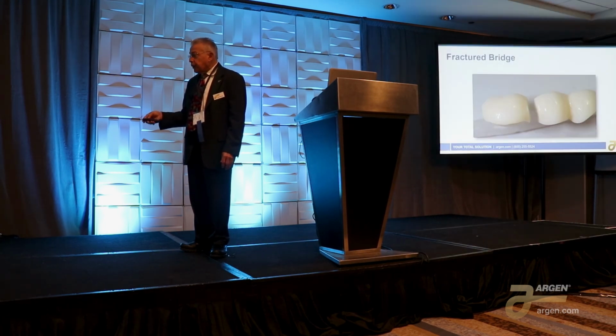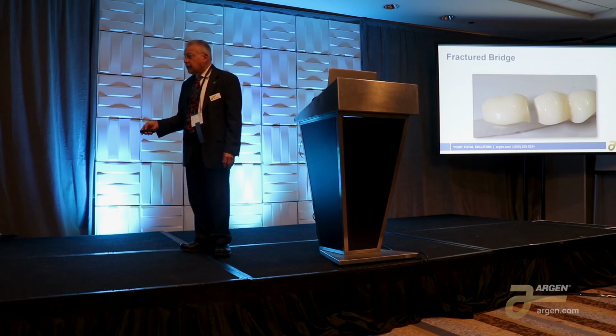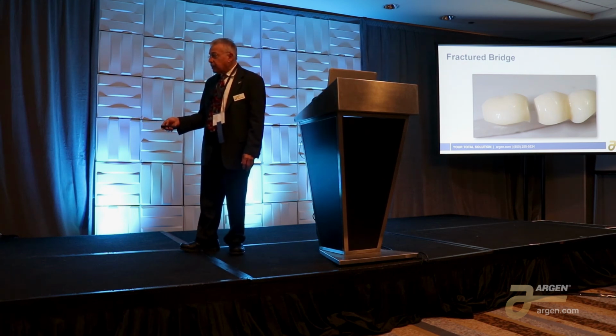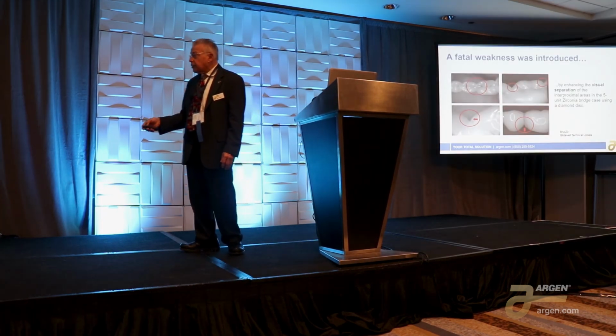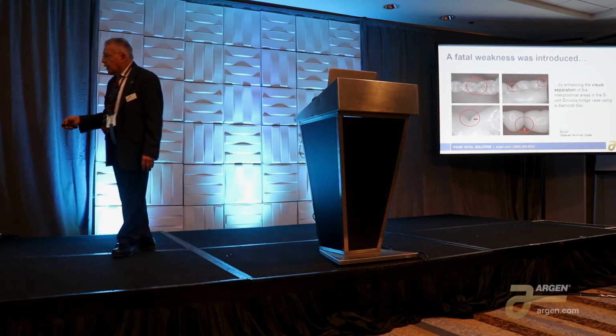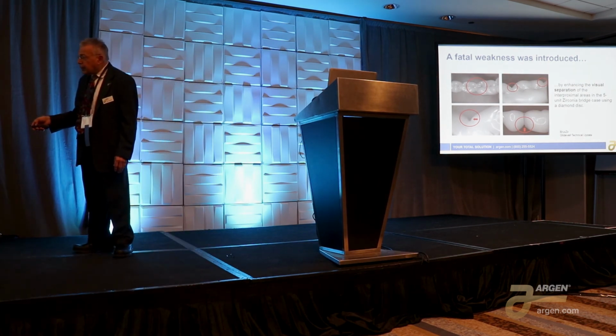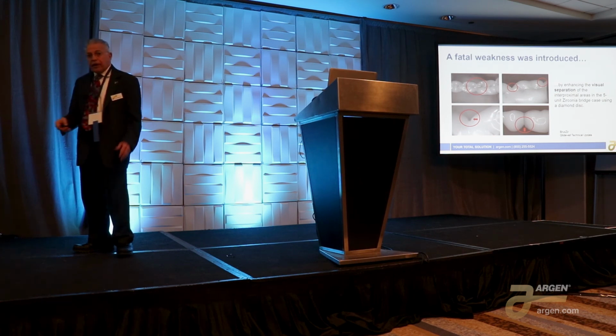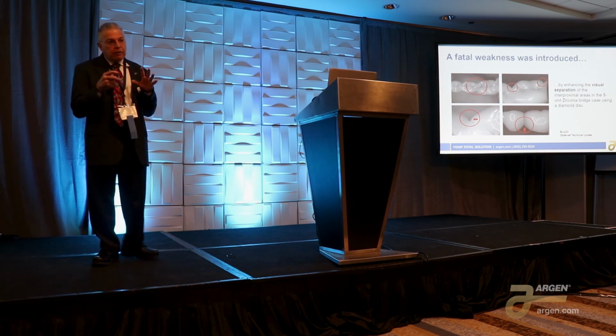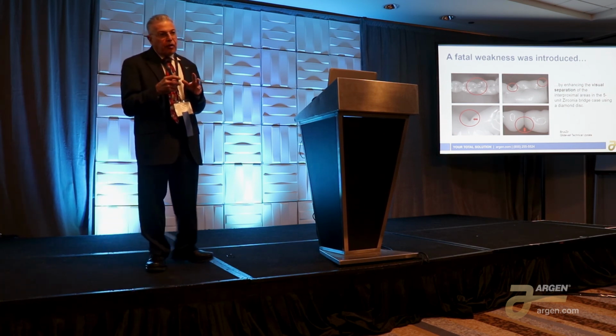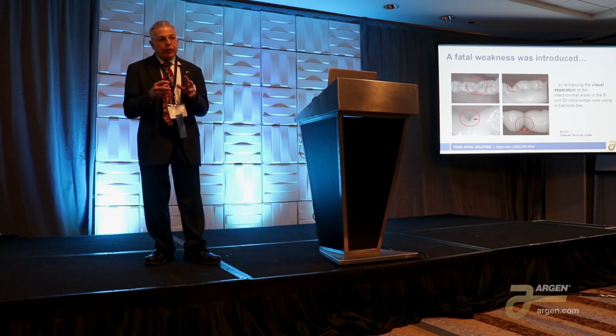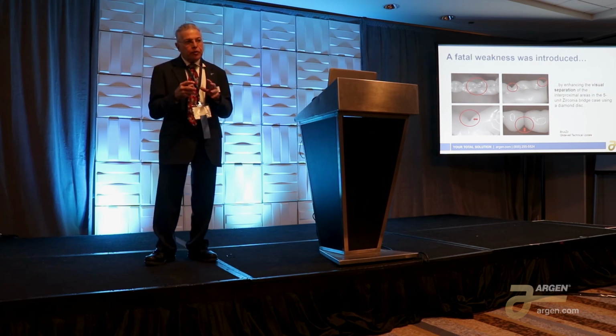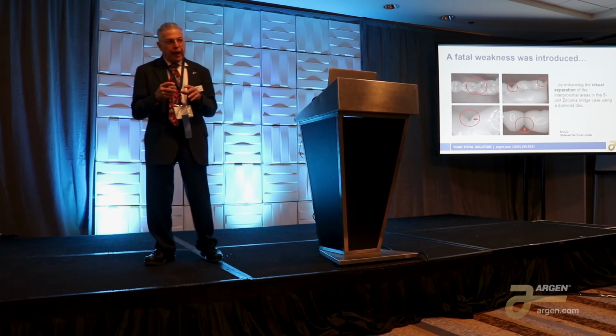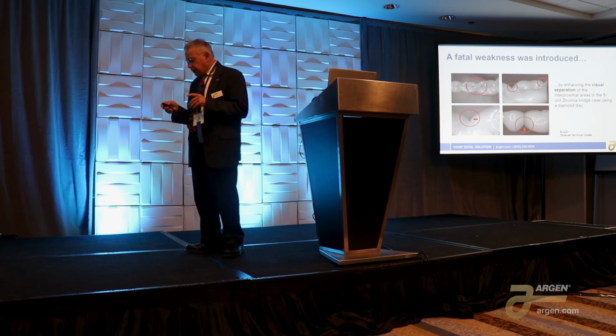Here you have a fractured bridge, again, because they used a disc. And this is from our friends at Glidewell. And if you look at it very closely, you could actually see the formation of the cut that the disc made as it went through. So by trying to open up the embrasures, I know you want to make it look very, very pretty, but where zirconia is sintered, you have a very difficult time trying to open up those embrasures without taking the risk that it's going to fracture. Just be aware of that.